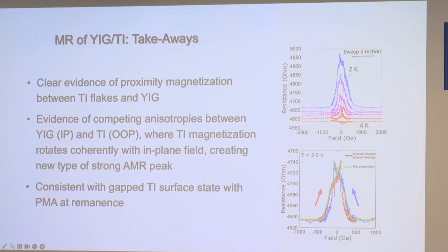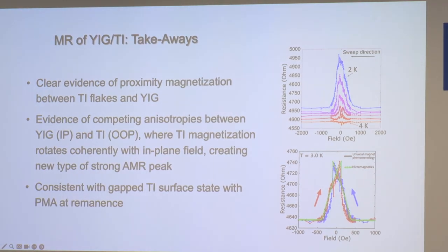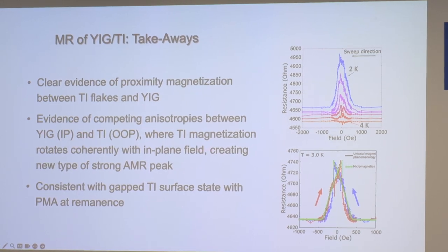Okay. And so the takeaway here is that there seems to be really clear evidence of proximity magnetization. There's evidence of competing anisotropies between the YIG and the TI, with the TI magnetization coherently rotating with an in-plane field, creating this new type of strong AMR peak, and it's consistent with having a gapped TI surface with an out-of-plane magnetization at remanence. So again, to answer the question, how do we know that there are surface states here? Because the temperature dependence and the peak behavior are at least more consistent with surface states than with any other states that could appear in these systems.